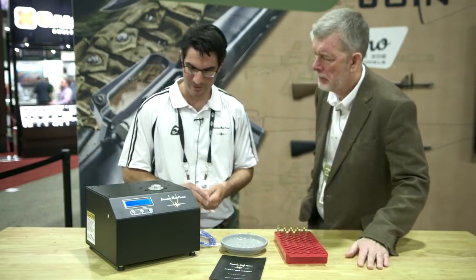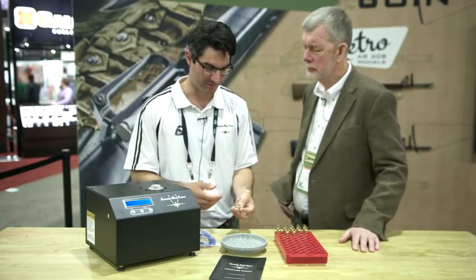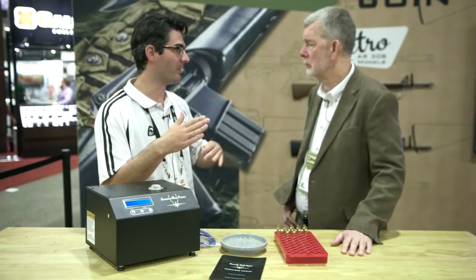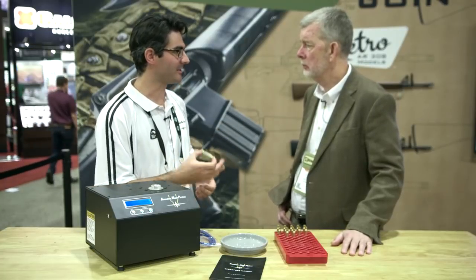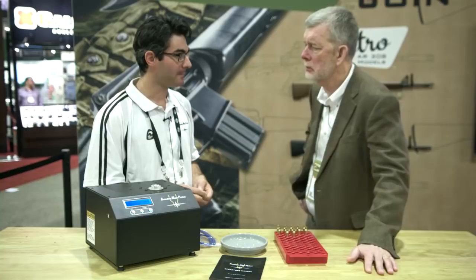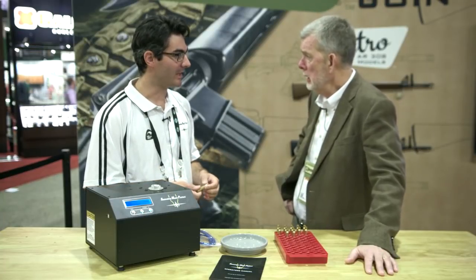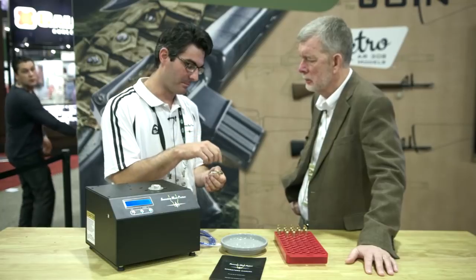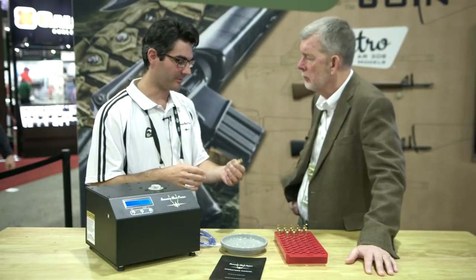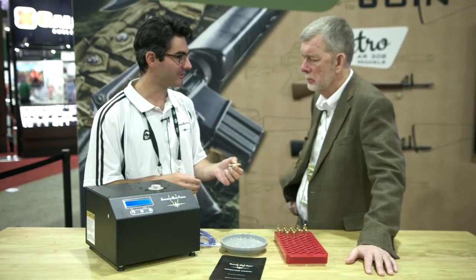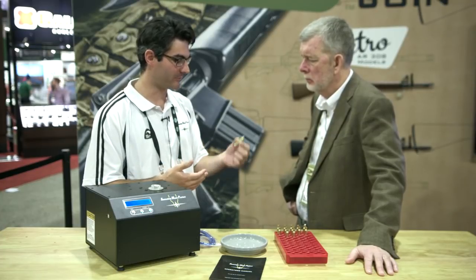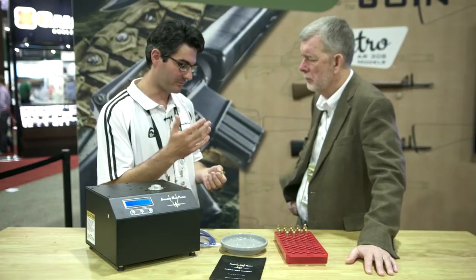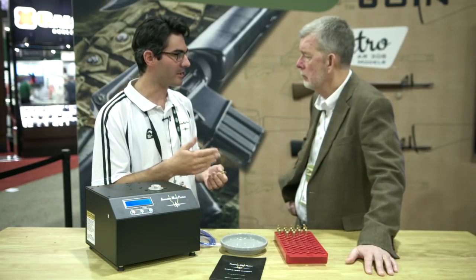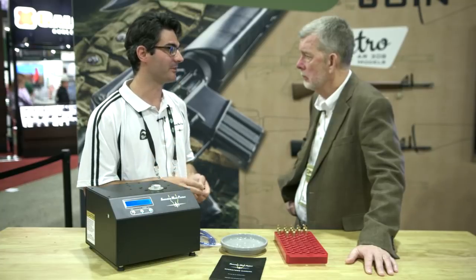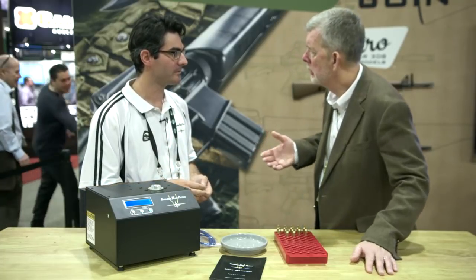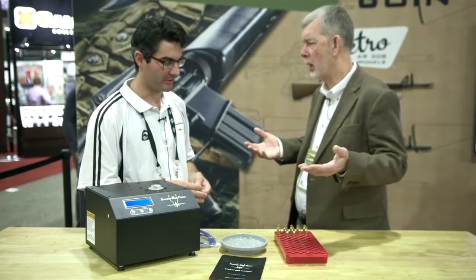Okay. So what we do differently is rather than try and aim for a temperature, which can be all over the place depending on the time, we actually go for the hardness. So we actually have a lab. It's got a micro Vickers hardness machine. Wow. And we actually go ahead and take the brass and measure it for the hardness before. Often if you have a case which has been shot and resized, it'll be quite hard, even after one reload, if it's virgin brass, brand new. After one reload, it'll actually be somewhere around the 150s. We've seen cases in the 200 Vickers that have been repeatedly fired. So you can actually analyze the metallurgy, which is something we can't do at home.